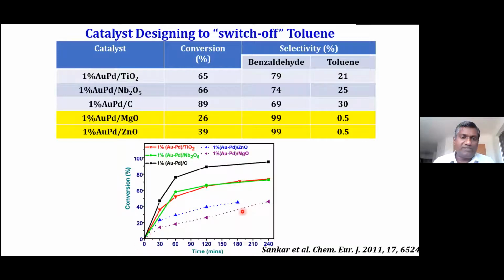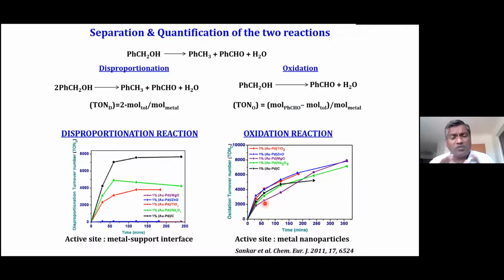The time online plot for all these catalysts is given here. Carbon is the most active, and magnesium oxide is the least active catalyst. Now, from the stoichiometry of these two reactions, we can easily separate them more or less quantitatively. So this is the reaction for the production of toluene. 2 moles of benzyl alcohol give 1 mole of toluene, 1 mole of benzaldehyde, and 1 mole of water. From the amount of toluene, we can calculate how much benzyl alcohol is consumed for this particular reaction. Then, from the total amount of benzaldehyde, if we subtract the amount of toluene, we can calculate the amount of benzaldehyde produced exclusively by the oxidation reaction.